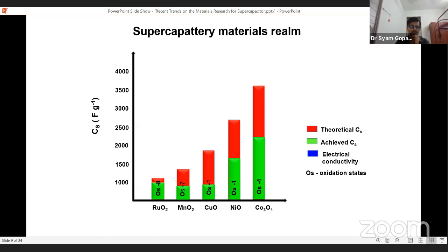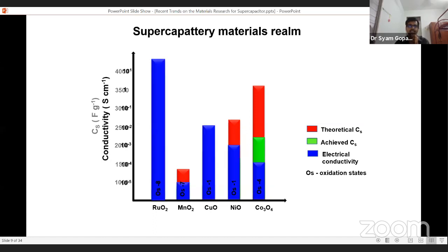But when comparing the achieved capacitance of cobalt oxide, the other materials have achieved only lesser capacitance. Then while comparing conductivity, the conductivity of ruthenium oxide is much better compared to other materials, and that's why it is being used as a pseudocapacitive material. But the factor hindering its commercialization is its availability. That means in the Earth's crust, the availability of ruthenium oxide is very low compared to the other materials.